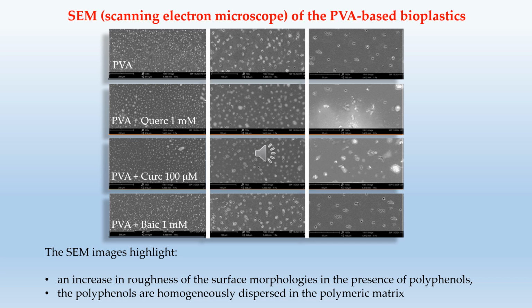Again, as can be seen, the scanning electron microscope images highlight little changes in the surface morphologies in the absence or in the presence of the tested compounds, with a general increase in roughness in this last case. This more heterogeneous structure can be attributed to the interaction between the polyphenol molecules and the macromolecules, which hindered the alignment of the polymer chains to form polymer-polymer intermolecular interactions, favoring the formation of a semi-crystalline material. Moreover, the analysis shows that the polyphenols are homogeneously dispersed in the polymeric matrix, according to the other tests described in the above slides.